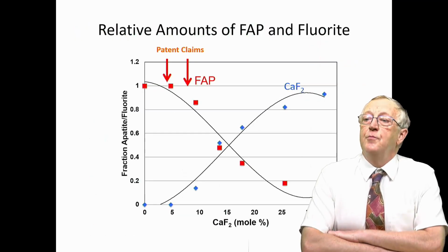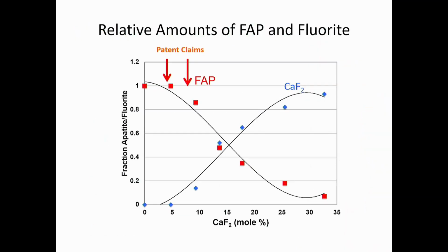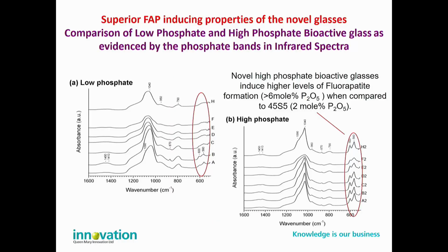We said earlier that if you put too much calcium fluoride into the glass, then what you form is calcium fluoride. What this graph shows is that as you increase the mole percent calcium fluoride in the glass, the fluorapatite produced declines at the expense of calcium fluoride being produced. The two patterns we find correspond with the two arrows on the diagram. The first one is for low phosphate glasses, and the arrow at higher calcium fluoride contents is for higher phosphate content glasses.